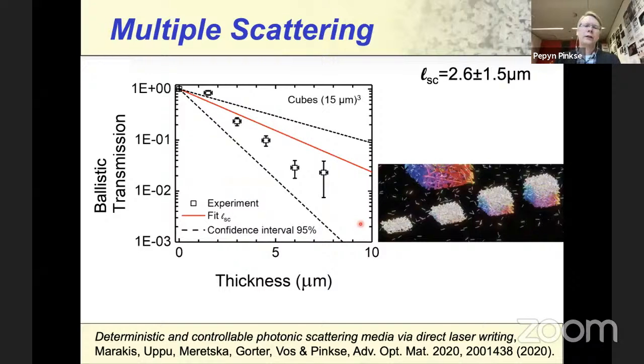And if you then look at how much of the ballistic light is going through, if you have a very thin sample like the one here on the left in the black and white in the colored picture, there's a lot of light going through, which of course is getting less and less if you make the sample thicker and thicker. And by the transmission of this ballistic light, you can find that the scattering mean free path is on the order of 2.6 micrometer, which is indeed shorter than the length of the sides of the cube, which is 15 micrometer. So these cubes are artificially made, and indeed in a multiple scattering regime.